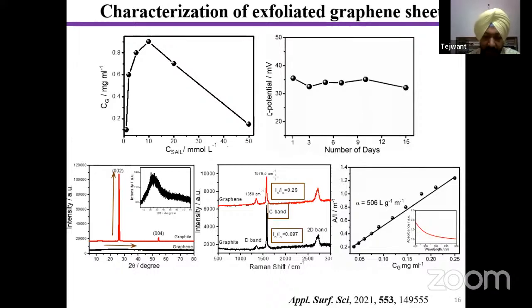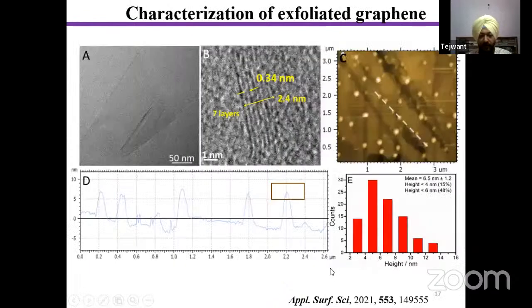They increase a bit in the case of graphene. There the ratio is 0.29, but still this ratio is very less as compared to the graphene exfoliated via other methods. For other methods, the defects in the graphene are introduced to a large amount, and the more defects present in graphene, the more deterioration to the properties of graphene would take place. So we need a lesser number of defects, which can be obtained by the graphene exfoliated using the bath sonication method in the presence of a surfactant.